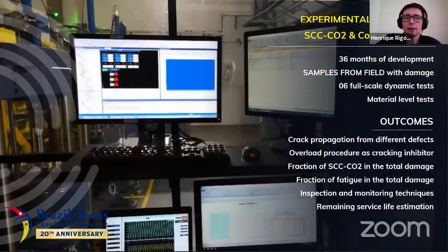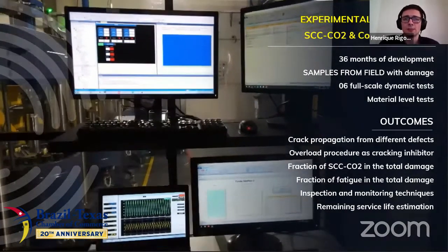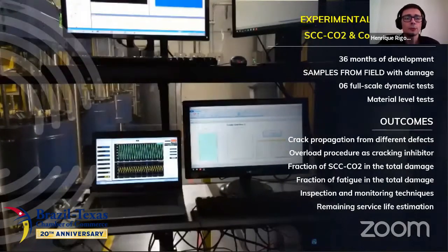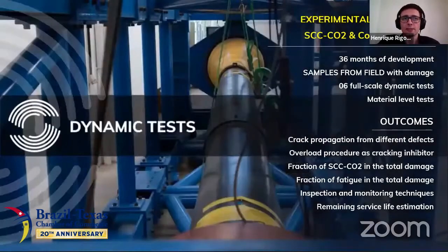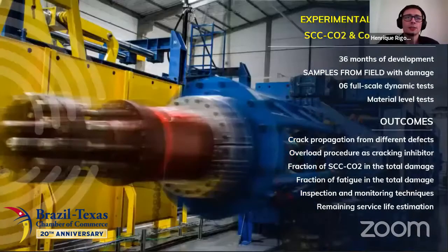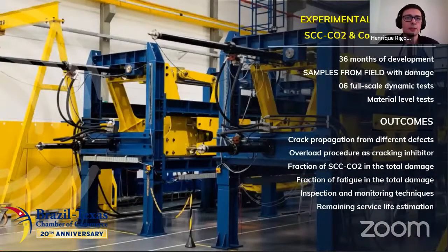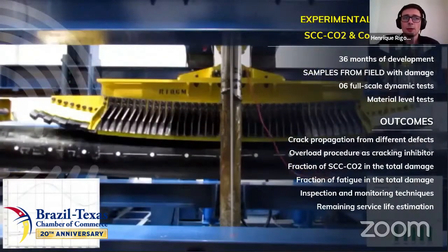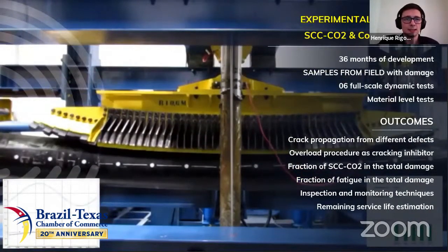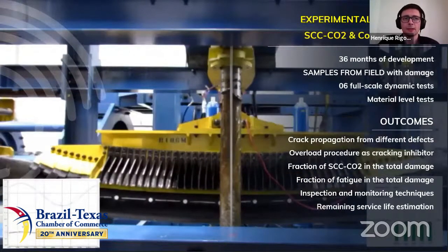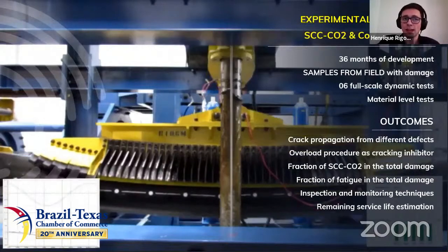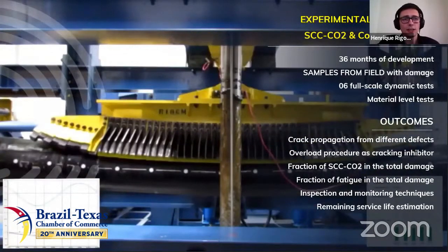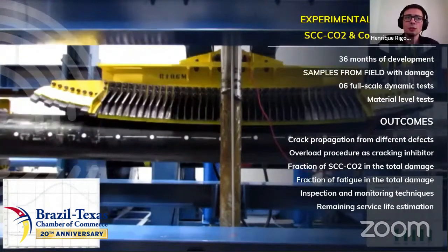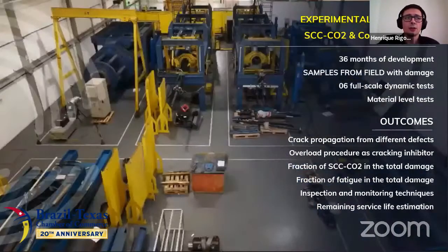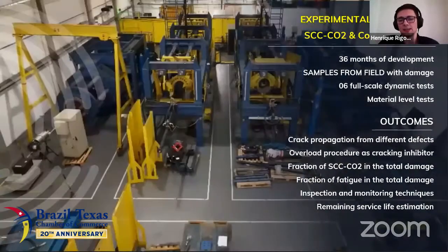After the dissection of the retrieved pipes, we will carry out several experimental assessment campaigns, from material level up to full-scale tests. The goals of these campaigns are to evaluate the crack propagation rate in the presence of different types of defects, to explore the effect of overload cycles as an option to inhibit crack propagation in the field, to develop and implement inspection and monitoring techniques that can detect the presence and growth of defects, to investigate and measure the proportion of damage due to SCC CO2 and the proportion of damage due to fatigue corrosion, to estimate the remaining service life, and also to update the safety factors from the dynamic test data.